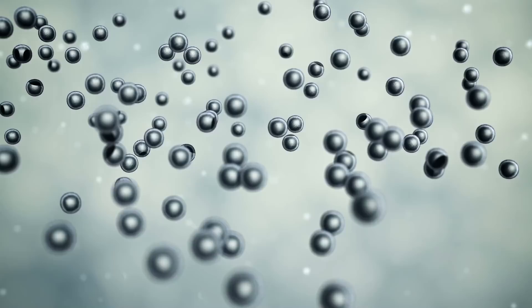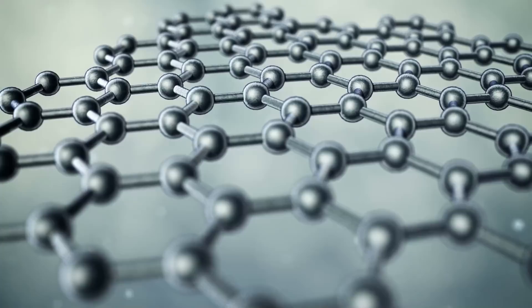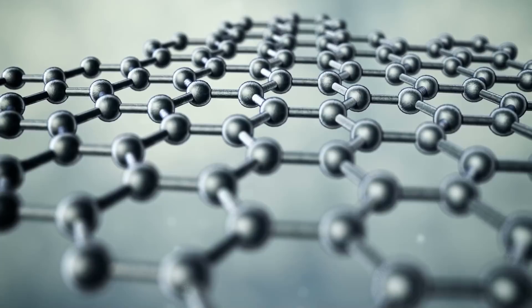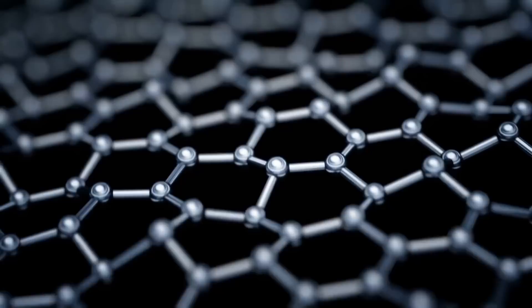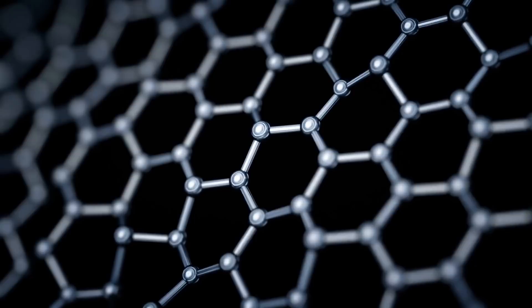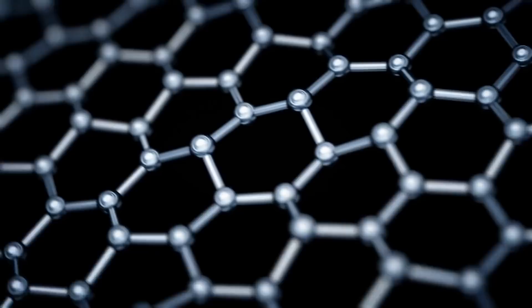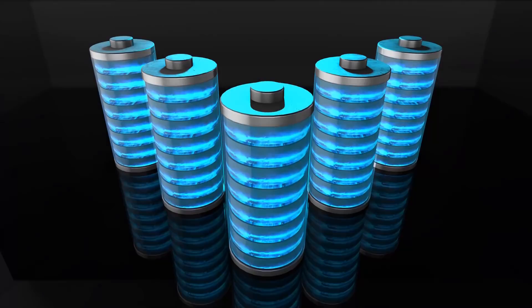Pristine graphene is extremely difficult to make, and is typically done by chemical vapor deposition of carbon atoms onto a copper sheet, which stabilizes the lattice. However, making variations of graphene like functionalized or reduced graphene oxide is typically done by chemically exfoliating graphite with sulfuric acid, and this process is widely used to make graphene oxide sheets for supercapacitors and batteries. This graphene has defects and functional carbon groups, which keeps it from being true graphene, but also makes it harder for it to agglomerate, easy to suspend in solutions, and with treatment it can be porous which facilitates electron and ion transport through the sheets.